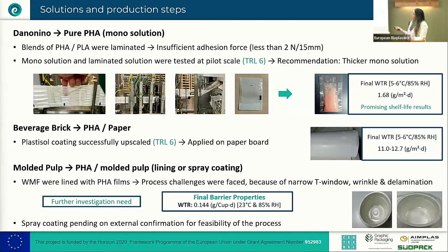For the beverage brick, also, we worked with plastisols coating, and the upscaling reached TRL 6 and was applied in paperboard. For the molded pulp solution, as already mentioned, we have two techniques. One was to try to use this coating, but with a new technique for doing it in 3D solutions. This could be done by spray coating, but this is still in definition. Because of time limitation, we couldn't finish this target path.